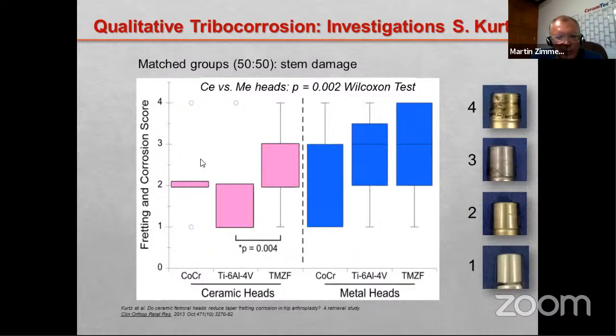If you look now more specifically at the material of the stems, if you use what we call the conventional titanium aluminum material with vanadium, we have much less fretting corrosion than with the TMZF, also called beta titanium, which is a more flexible alloy and created a lot of fretting corrosion.